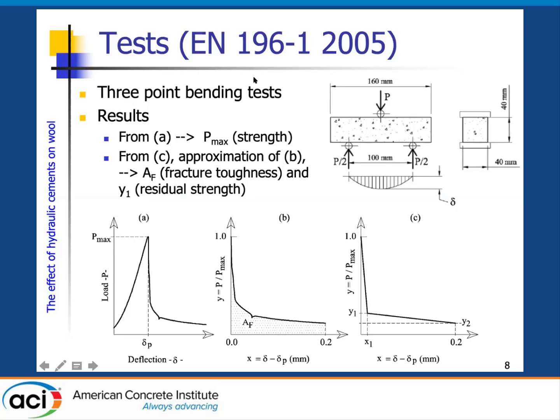These are the pictures related to the test. It was a very well-known test performed on mortars, and it is ruled by European standards. In this 3-point bending test, we obtain the load deflection diagram, and from this load deflection diagram, we can obtain the strength.